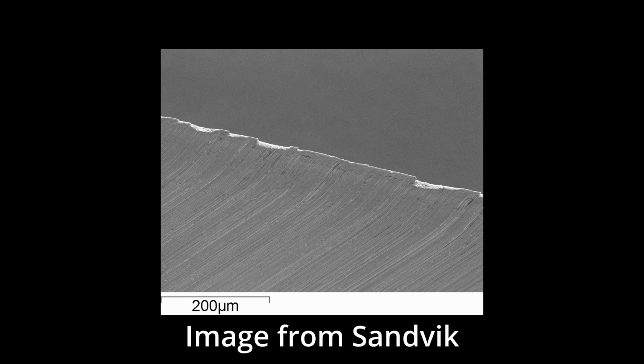Another of the major dulling mechanisms is microchipping. When you lose sharpness to microchipping, the steel does not have sufficient toughness for the intended use. Toughness is a measure of how well a steel resists fracture. Microchipping is especially common in knives with thin edges, so steels with high toughness are preferred for applications that lose sharpness to microchipping. Fracture can be quite sudden, leading to very rapid sharpness loss, so generally we prefer edge wear to be our primary mode of dulling. Microchipping is most common when cutting hard materials and any time that chopping is involved.